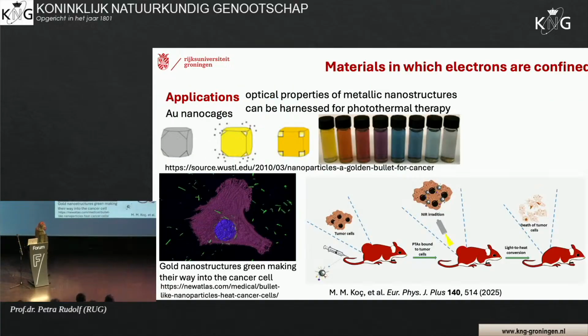It's also useful for medicine. You can make these little cubes, and again, depending on how thick, so these are hollow cubes, and depending on how thick you make the walls, you get different colors, which are now these plasmon excitations which decay. And this is used a lot in transporting drugs, or in using the fact that they absorb near infrared radiation, so no longer in this visible part, but at longer wavelengths. Because these nanoparticles, they can go to cancer cells, and then we can do 2 things. Either we use the fact that we tune the size of the nanoparticle to absorb near infrared light, and when you absorb infrared light, it becomes hot.